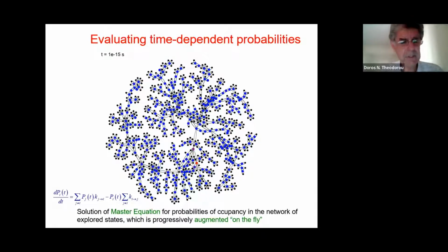So one can attempt to solve this set of master equations within a network of minima, which is continuously expanding in time, so as to accommodate the fact that at long times the system will go farther and farther in its configuration space. And we have developed such a simulation approach which solves the master equation in a gradually expanding set of minima, and observes how the probability distribution among these minima changes with time.